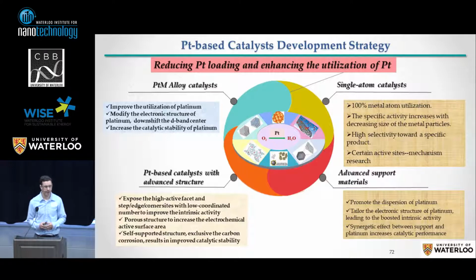Okay, so in terms of fuel cells now, the main strategy for reducing the cost of fuel cells and improving the efficiency of them is to reduce the amount of platinum you need. So platinum is needed right now as a catalyst on the air electrode to reduce oxygen, to be able to consume the electrons coming from the hydrogen. But platinum is one of the most expensive metals. So in order to reduce the amount of platinum, mainly you need to increase the surface area or increase the exposure of platinum to the oxygen, which requires nanotechnology solutions.